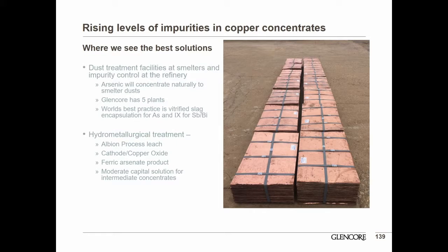Copper hydrometallurgy has been a dream of the industry for a long time. It's one though that's seen 7 or 8 very well publicised starts that haven't been successful. We believe that the combination of a very simple Albion process oxidative leach with conventional SXEW will give the copper industry the hydromet solution that it's finally looking for. We can get over 99% recovery of copper from copper concentrates and a very effective separation of arsenic.